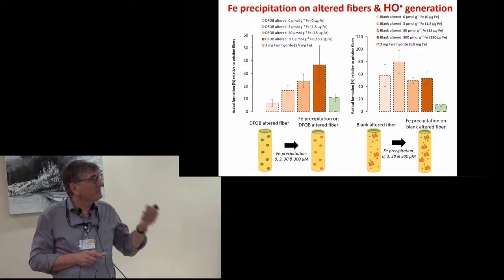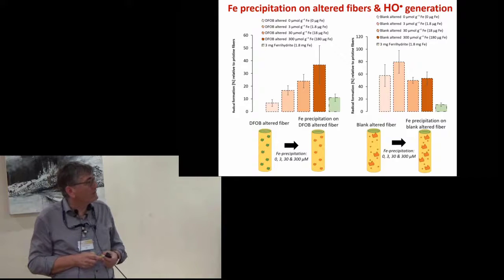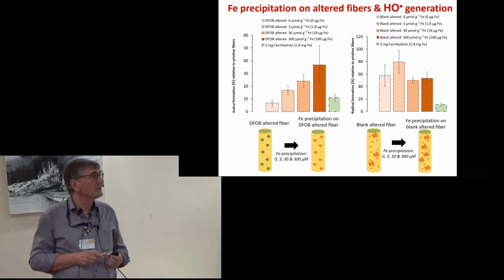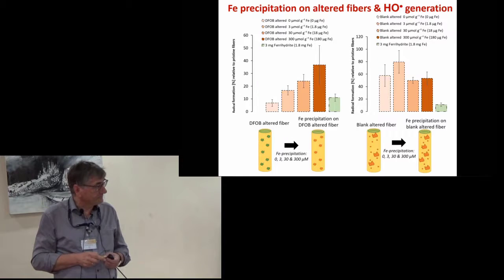The precipitation of only three micromoles per gram extra iron—corresponding to 1.8 micrograms iron—increases the yield by more than 10%. A similar yield for hydroxyl radicals is found with 1.8 milligrams of octahedral iron in ferrihydrites. So we see that the reactivity of tetrahedral iron atoms in the silicon layer is approximately 1,000 times higher than in the case of octahedral ferrihydrites.